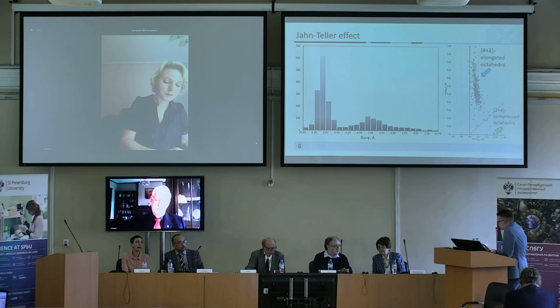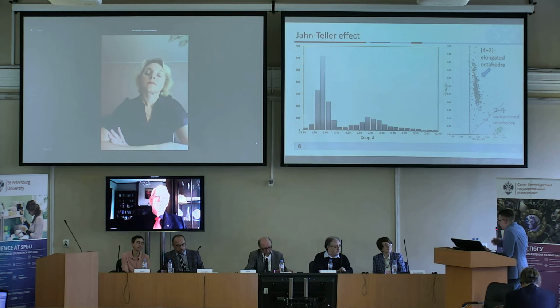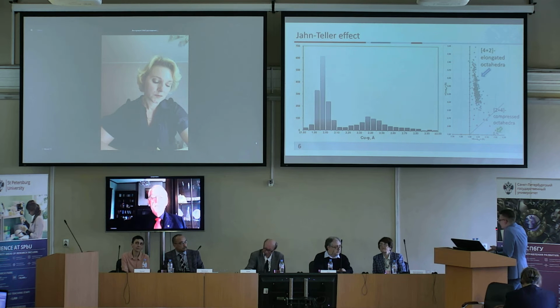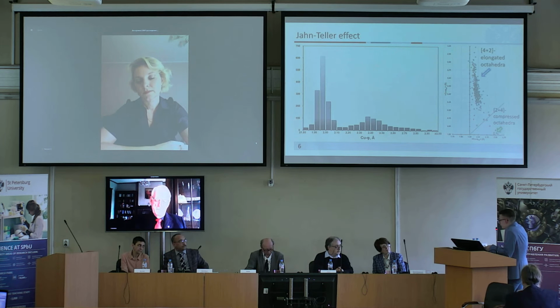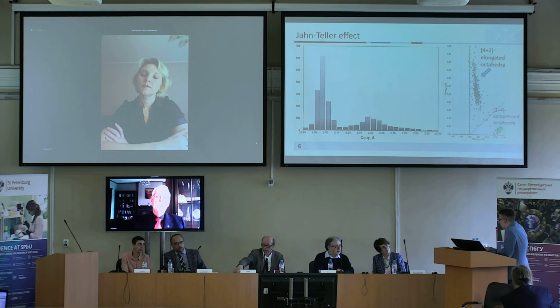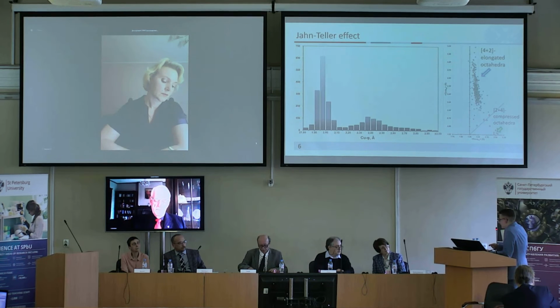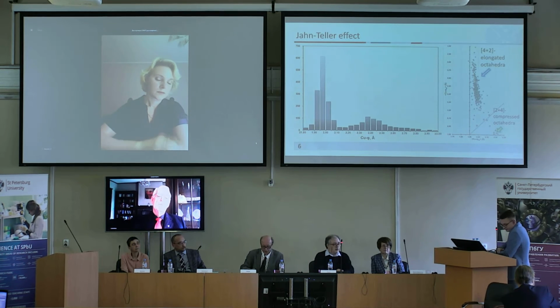If we talk about oxygen, we took 3 angstrom, because a council member, Professor Horton, in 1995 made some quantum chemical calculations, and he determined 3.2 angstrom. And our colleagues, chemists, keep saying that the maximum can be 2. So the rest is van der Waals interactions. So we calculated and decided to set the limit at 3 angstrom. And if we talk about copper chlorine, we set the distance at 3.1 angstrom. Thank you.